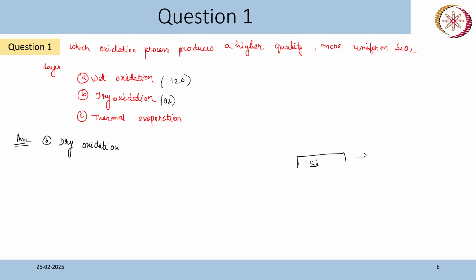Now what happens when you do oxidation? There will be growth of an SiO2 layer. This is silicon, and there will be SiO2. Okay. Now some portion of your silicon will be consumed here. So if this thickness is, say, T_ox of SiO2, then 46% of T_ox is actually from silicon, and the rest, 54%, will be of oxide. So this thickness will be less. If this is your initial thickness of silicon, T naught say, then your T naught of silicon will be more than T of silicon. So this is the difference between growth and deposition. That's what I just wanted to discuss.